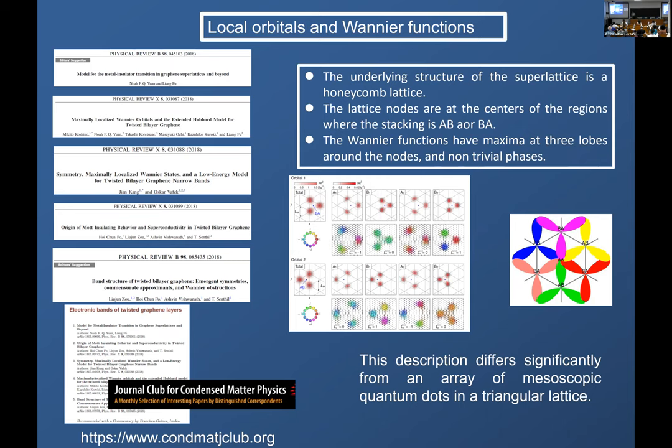Let me mention that the question of defining the Wannier functions, something which I will work out for instance here in 3D, is quite more challenging than what it looks. First, because you cannot do it starting from the continuum model. The continuum model assumes that this valley is independent of the other. Each valley is topological in the sense that it's like a Landau level—it has a finite Chern number, it has Berry curvature which does not average to zero. Because of that, the Wannier functions you define need to have power law tails. They are not exponentially localized.